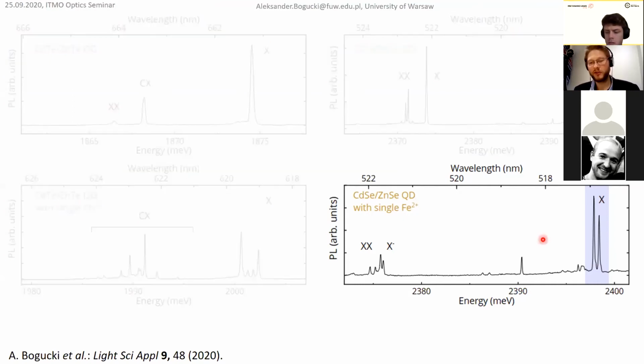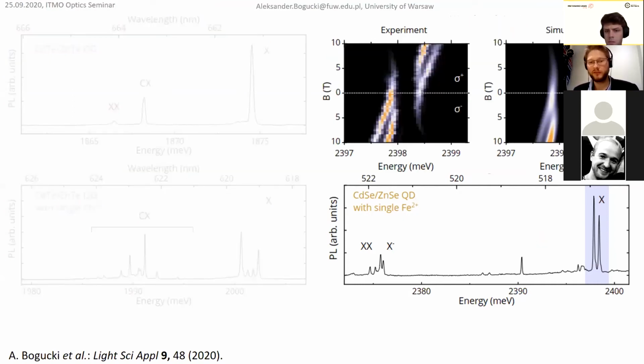Here is an example scan in magnetic field from 0 to 10 Tesla. So this is from 0 magnetic field. These are these two lines, and as you can see, we can trace them easily, which sometimes is difficult, but here with microlenses it's quite easy. And simulation confirms that it was a quantum dot with a single ion, and it confirms that polarization is conserved. So this sigma plus and sigma minus is still sigma plus and sigma minus, and we can't tell the difference. I mean, as far as we can measure, it's conserved, so it's not destroying the polarization.